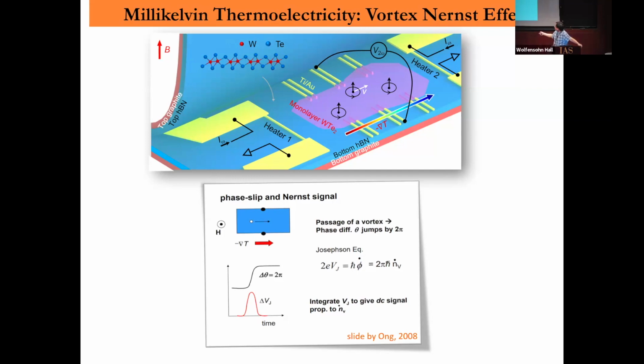So you can, without applying any electrical current, just by applying a temperature gradient—that's what this whole device is aimed to do for 2D material, which is why it looks a bit more complicated. The point is to apply heat through this heater, and then generate a temperature gradient along the 2D plane, driving this material into the superconducting state.